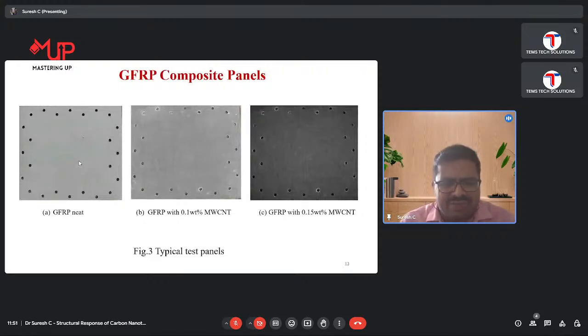So here for studies, we considered glass fiber reinforced composite. Presently, all the submarines and such are using metal structures. But the drawback in metal structures is that they are prone to corrosion. So after a certain time, all the metal parts will start corroding, especially in seawater, because of the salinity, the corrosion rate will be much higher compared to normal water. So these composites are corrosion resistant and they can give more life to the material. That is the reason why composites are now replacing metal parts wherever they are used.